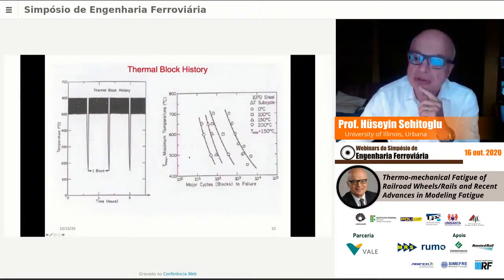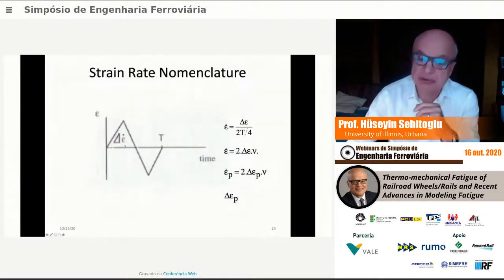And you could see here, if we look at the maximum temperature against blocks to failure, the minimum temperature is kept at 150 in this experimental work in the laboratory. If you didn't have these little subcycles here, that's your fatigue life. And if you have these subcycles at 100 degrees, 150 or 200, as much as 200 shown here, the blocks to failure goes all the way from almost 10,000 cycles to about 100 cycles. So these little thermal fluctuations that the wheel tread experiences could be quite damaging, is what we're seeing here. This is again experimental work.